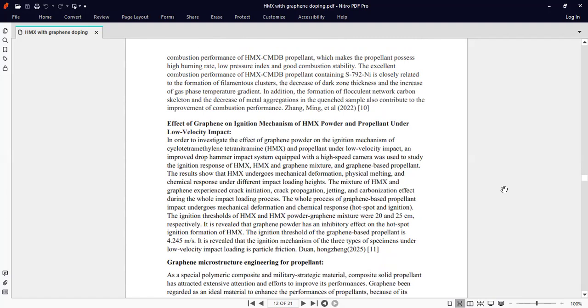The excellent combustion performance of HMX-CMDB propellant containing S-792-Ni is closely related to the formation of filamentous clusters, the decrease of dark zone thickness, and the increase of gas phase temperature gradient. In addition, the formation of a flocculent network carbon skeleton and the decrease of metal aggregations in the quenched sample also contribute to the improvement of the combustion performance.